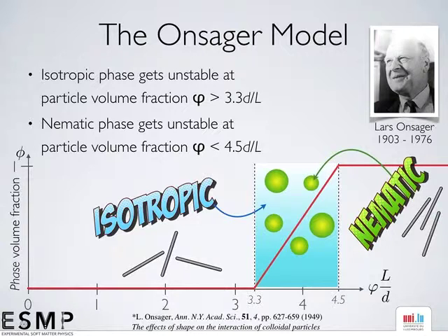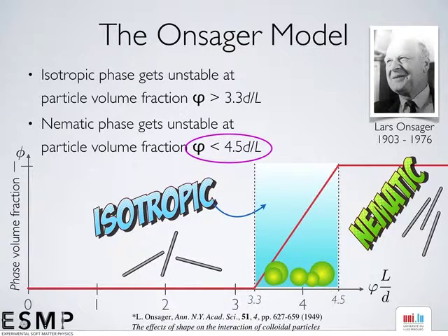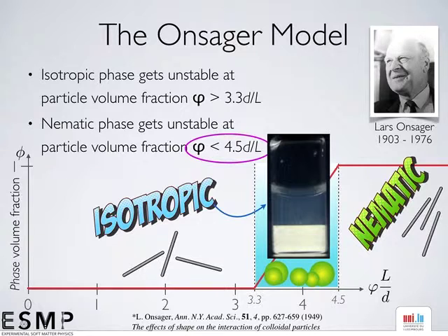And the question is then what happens there? What happens there is that the nematic phase starts forming as droplets or tactoids, as they are called. And importantly, they have the higher volume fraction of CNC. And since cellulose has a higher density than water, these will then fall, eventually sediment and form a lower phase. And this actually happens. This is what we see when we look at these samples between cross polarizers, that the liquid crystal phase sediments to the bottom. And this is nice because we can separate these two phases and look at them separately.